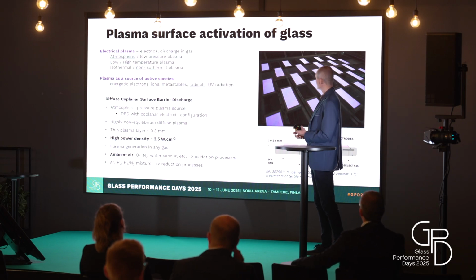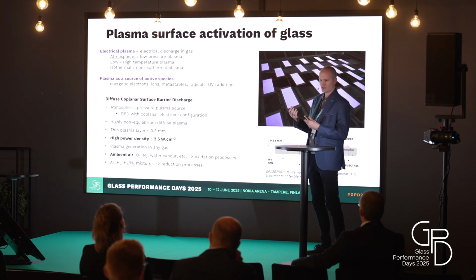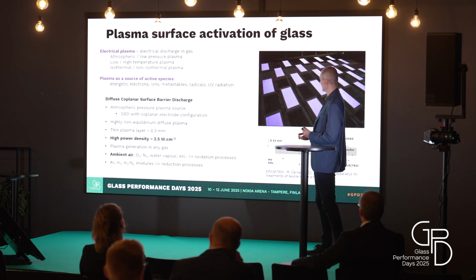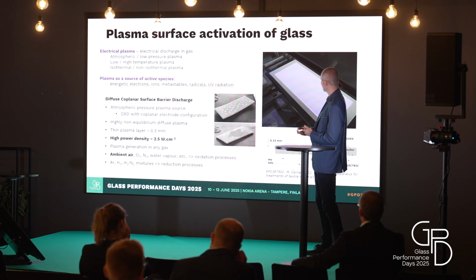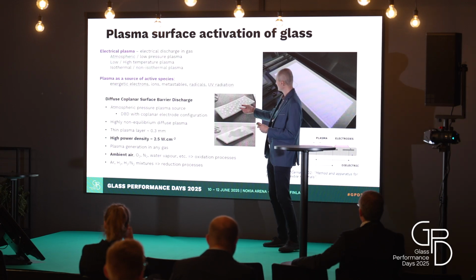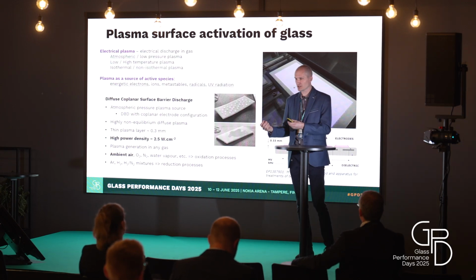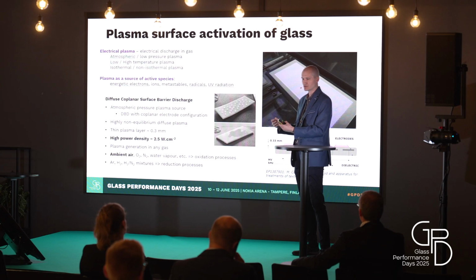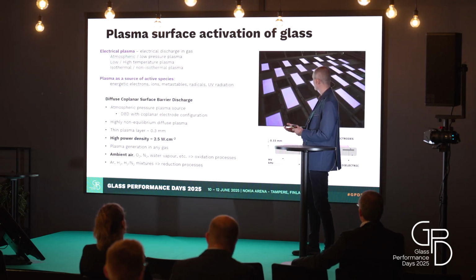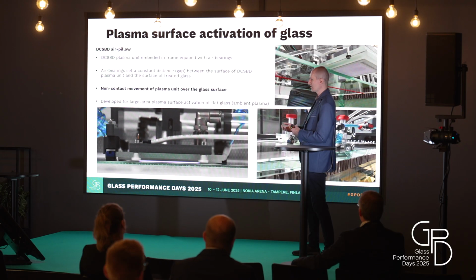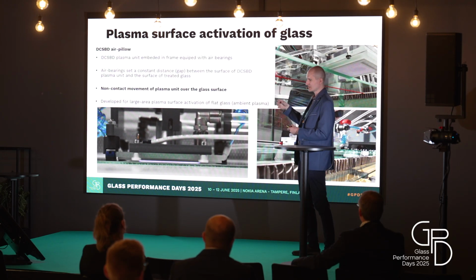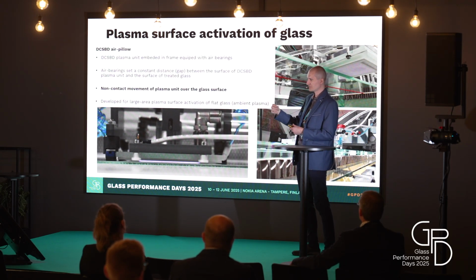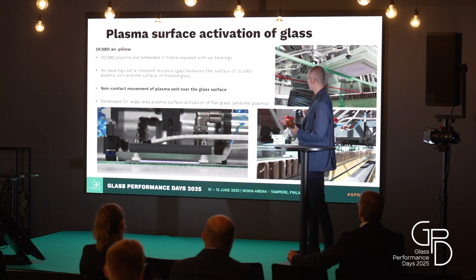So let's go next. And what is the typical effect of plasma on the material? The basic effect is, as we can see here on this surface, you can turn the material from hydrophobic to hydrophilic. You can clean it, and this is the typical result when we expose the glass surface to the plasma.